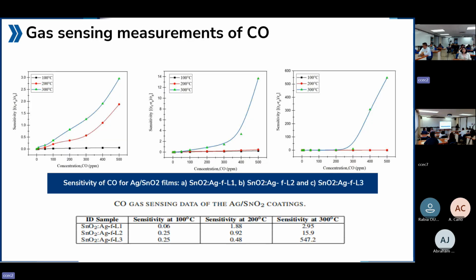Moving on to the gas sensing measurements, which are the application of this part. This is where all the structural enhancements discussed so far show their value. First, let us discuss the gas sensing measurement for carbon monoxide gas. Here, from the graph, we can illustrate that the sensitivity depends highly on operating temperature and the addition of silver layer. We can see that the 3-layer immersed Ag tin oxide coatings show a maximum higher sensitivity, which is very significant.